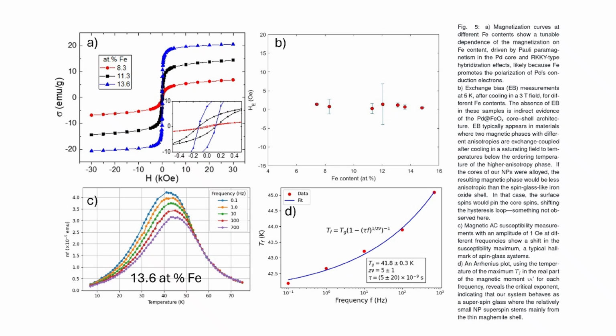Next, we perform exchange bias measurements at 5 Kelvin after cooling in a 3 Tesla field. The absence of exchange bias in all samples supports the palladium iron oxide core shell model. Typically, exchange bias appears when two magnetic phases with different anisotropies are exchange coupled below the ordering temperature of the harder phase. If the core and the shell in our nanoparticles were strongly coupled in that way, we could expect a shift in the hysteresis loop, but we do not see that in our study.